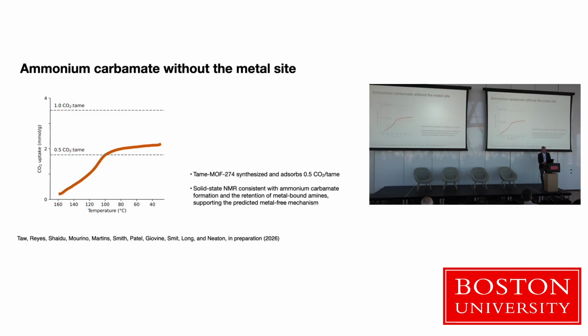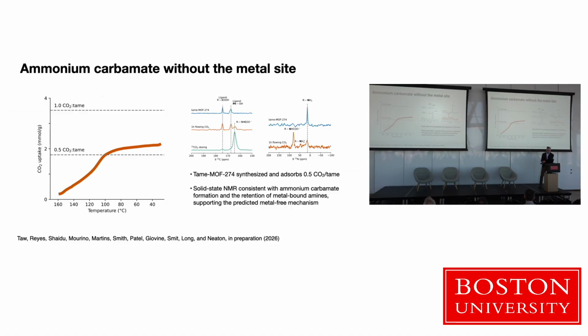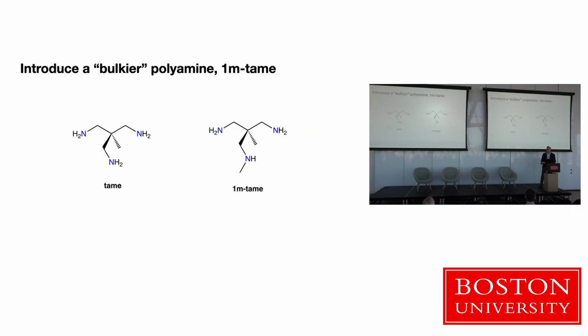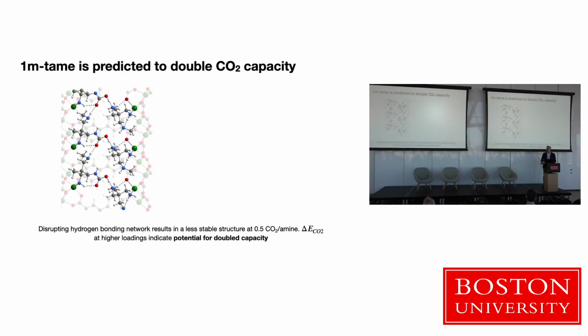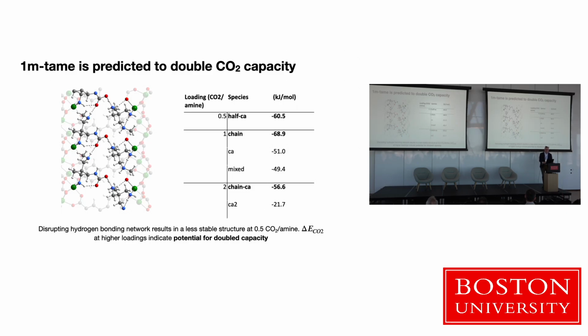Now, it turns out that this system had not been seen, but we asked the experimentalists to look into it, and they found some strong evidence of this kind of structure, in comparison with our NMR chemical shift calculations. So there's some evidence that that structure exists, and that was good. That emboldened us a little bit, but of course it's disappointing in the capacity. So we thought, we'll just disrupt the network of hydrogen bonds by introducing a methyl group, and lo and behold, that does lead to a much different situation, where you can support up to two CO2 per metal site, the sort of structure that we were looking for.